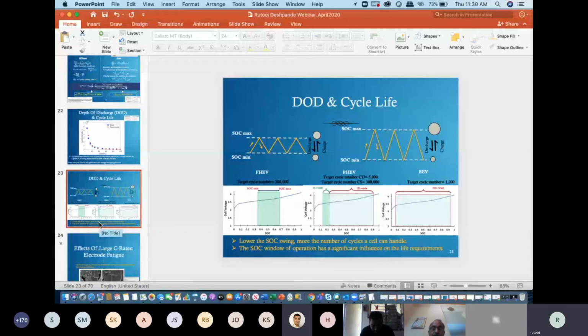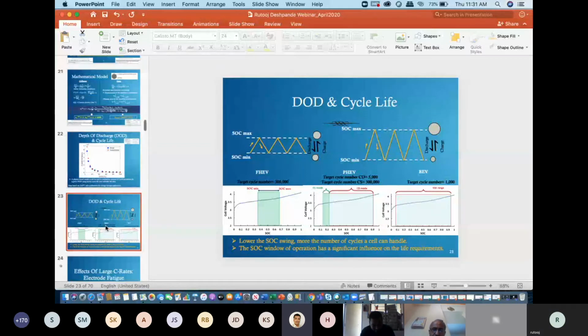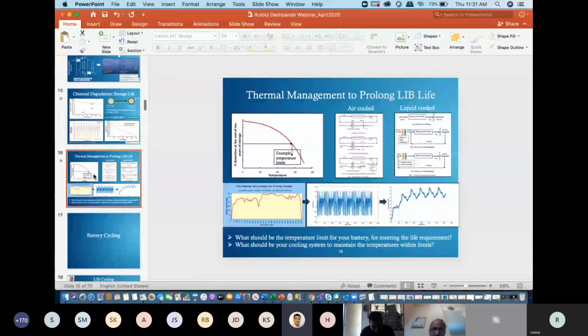The other question is, the temperature across the globe is rising, and we are seeing summers going as high as 45, 47 degrees centigrade. Taking a 10 degree rise because of the enclosure, etc., under the hood temperature could be even higher. That's what the question means to say: would that lead to cells going across 55 degrees centigrade? And in such cases, how to maintain the cells so that the battery life is ensured?